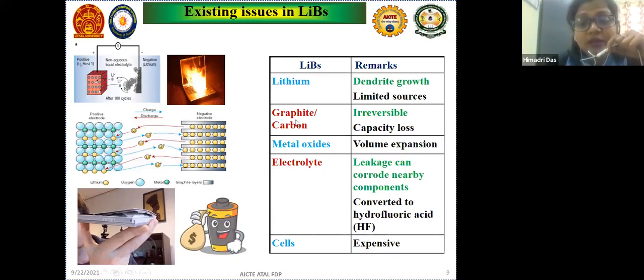Apart from the cathode, the anode, like graphitic carbon, also has irreversibility and capacity loss during charge discharge. That's why the battery has a limited lifespan. In general, if we see the battery, when we charge it in the first few months it is working very nicely, and then the devices are not charging well, or it's not keeping charge. That's nothing but because of this capacity loss of the battery.